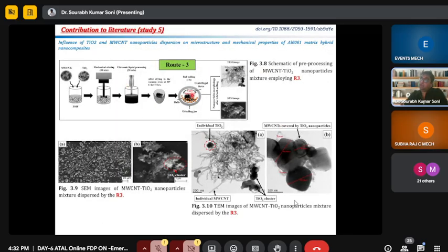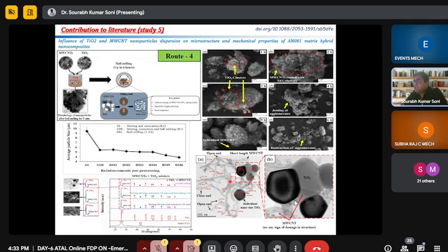In another route, route 3, first mixing, then stirring, then ultrasonication, then ball milling. This is the microscopic image of the powders obtained from route 3. Here we can observe individual TiO2 particles for ball milling of 1 hour, and this one is for 6 hours. Very few TiO2 particles are available over the nanotube. So there is a difference between the ball milling durations also. As per your literature review or research goal, you can choose the dispersion process.